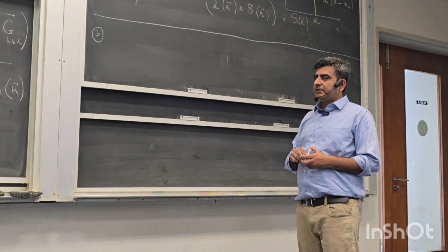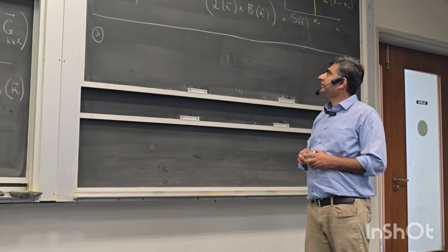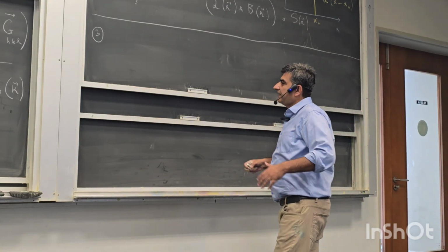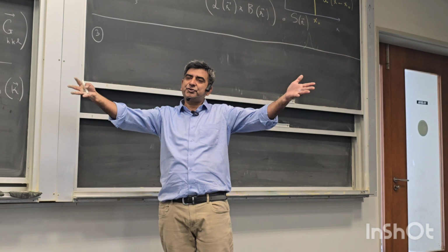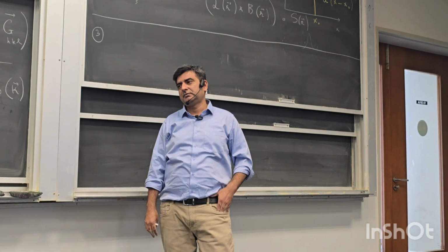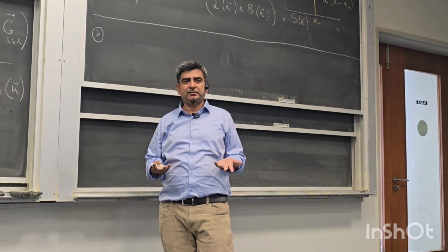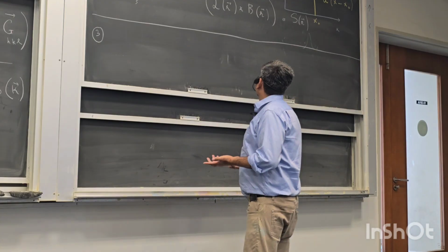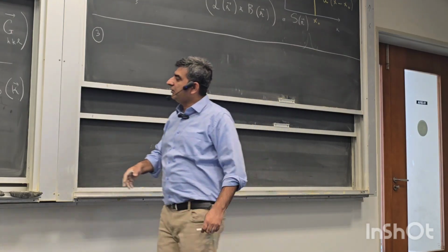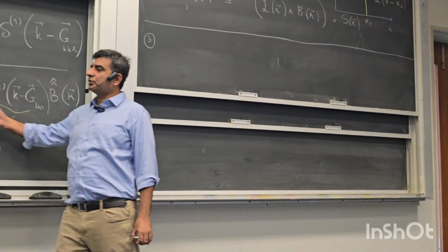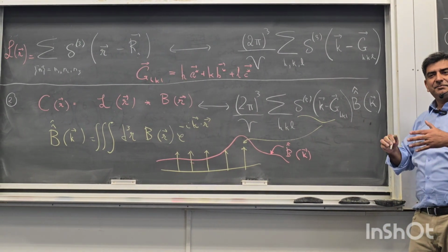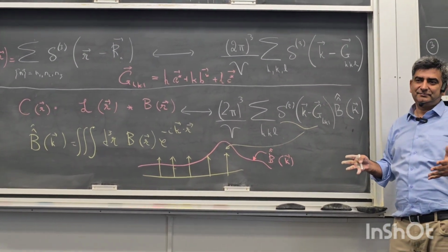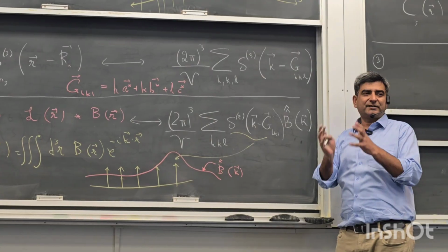And it turns out that since we're measuring intensities, if we take this crystal structure and take the modulus square of this, that will be proportional to the intensity of the peak for a given HKL. Since this sum is over all HKLs, the modulus square of this will give us the total intensity coming from that crystal.